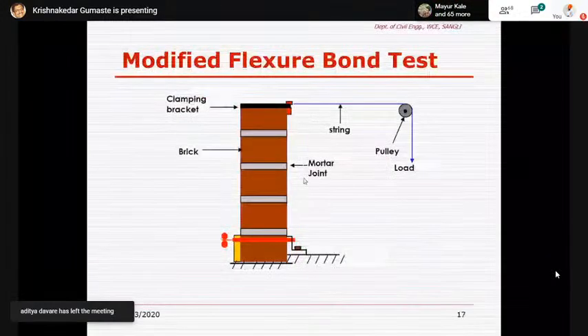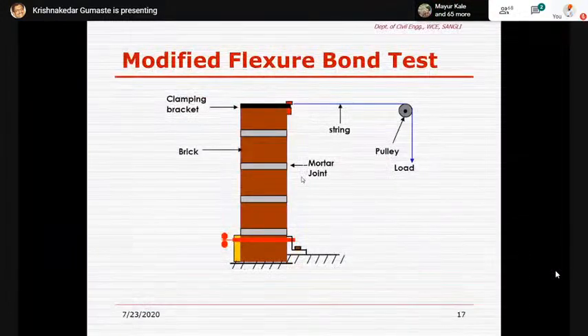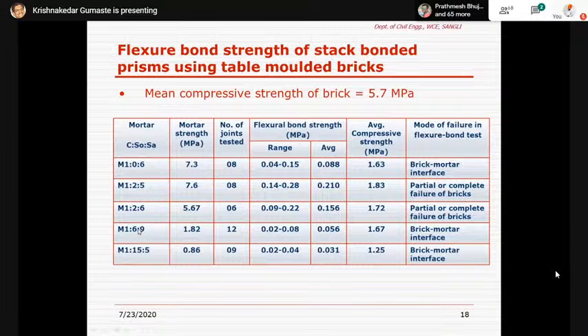The other idea behind assessing, as I was telling you, is that if the brick and the mortar are very, very strong, in that case the interface between the brick and the mortar also is important. And thereby, there are studies like the modified flexural bond test, which can be conducted in order to see what the interfacial strength is. It has been seen that for various different kinds of mortars and for a particular brick strength, the average compressive strength and the flexural bond strength were basically evaluated.